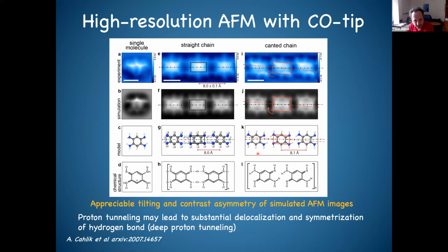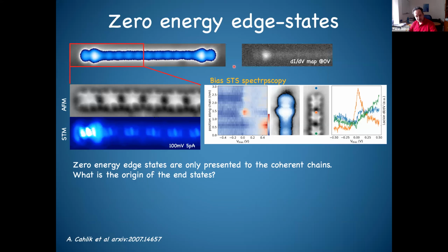So I'm done. So now with that, what we can show is that when we use path integral molecular dynamics instead of the DFT geometry calculation, and we calculate the AFM image, we see perfectly straight chains. They agree with what we observe experimentally. So this is another strong piece of evidence that this proton tunneling plays a role. There is another issue, and this is the last two slides: the edge state.